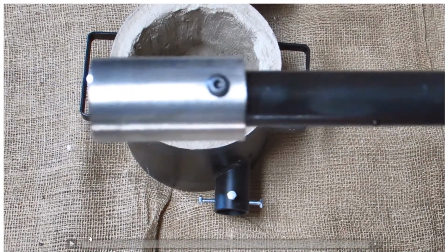This furnace also has a stainless steel tip, and the manufacturer recommends that you coat this tip with mortar. However, the thickness of the mortar isn't supposed to be that of ranch dressing, but more like that of paint. I didn't make a video of that, but I made a thinner slurry-like mixture of the mortar and dipped the burner into that, and then assembled the furnace.